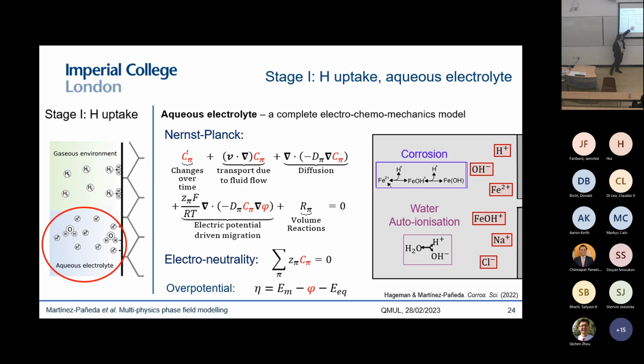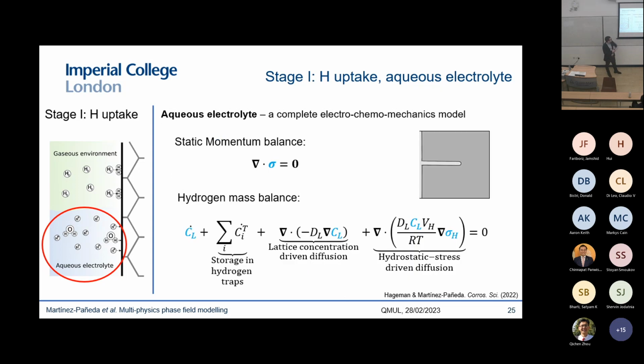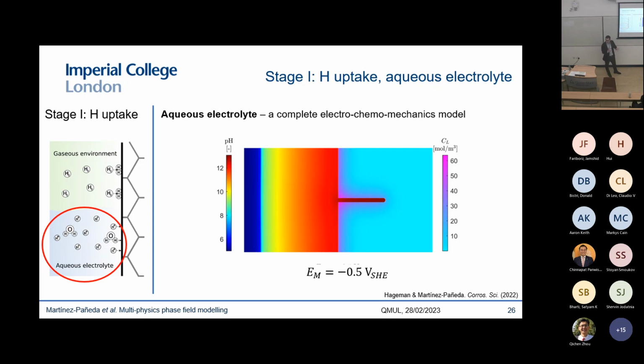You use Nernst-Planck to characterize the electrolytic behavior in the electrolyte, and then you solve the static momentum balance and the hydrogen mass balance on the metal. And this is the kind of results that you get. I'm only showing a representative result.